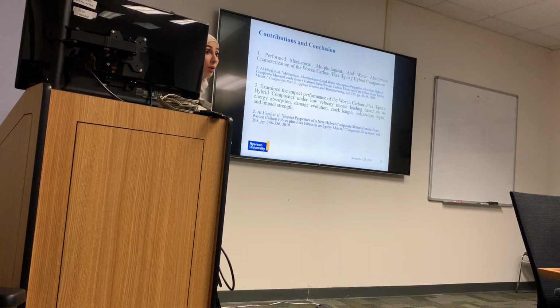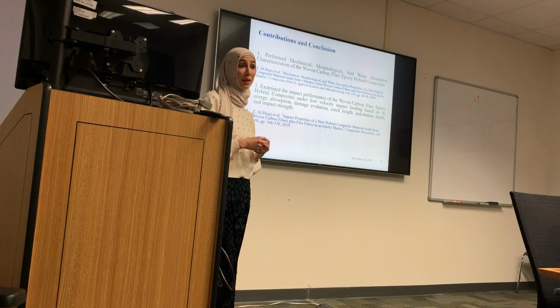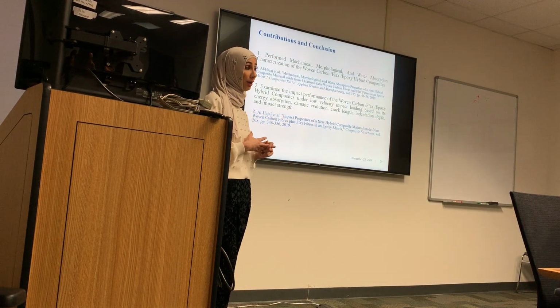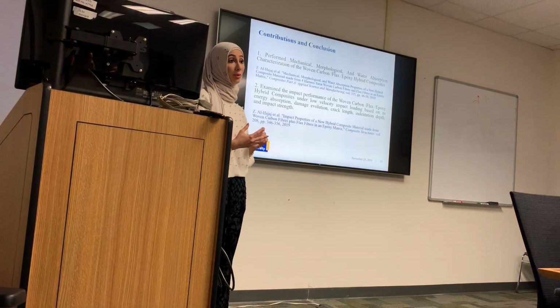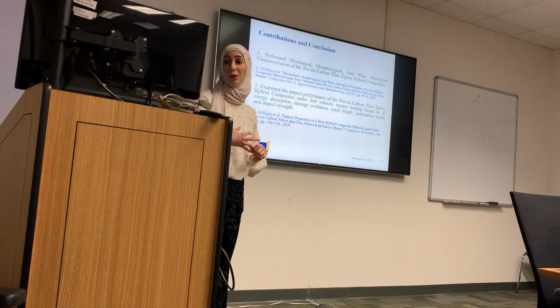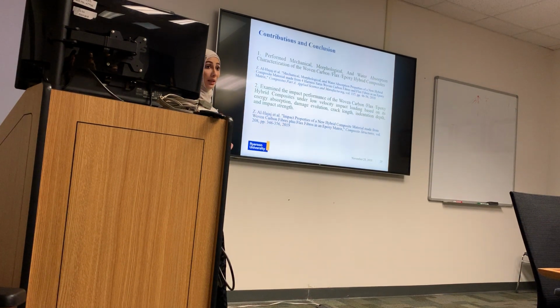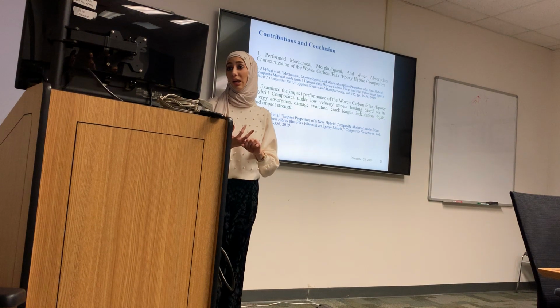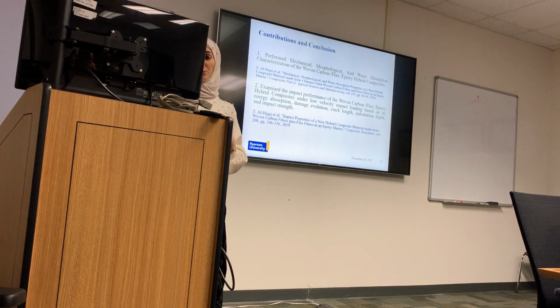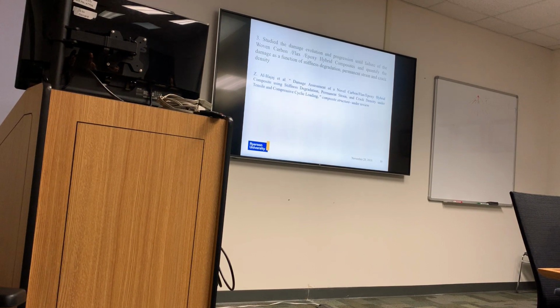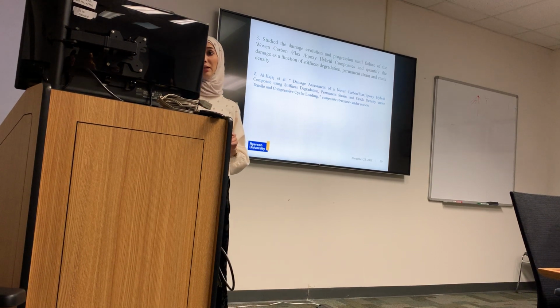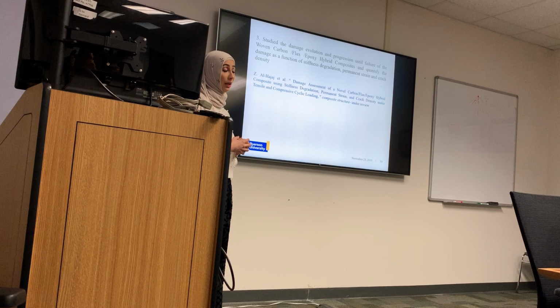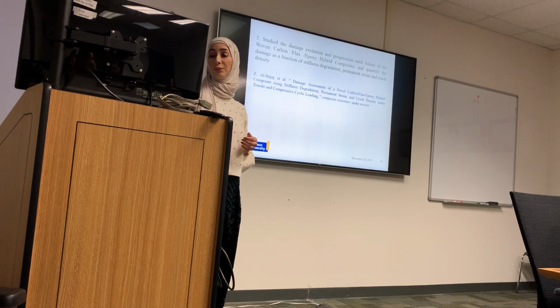In conclusion, I performed a deep mechanical characterization on my hybrid composite, including the water absorption, and that was performed in one published paper. I also examined the impact performance of the hybrid composites at low velocity between 5 to 40 joule, and that was presented in another published paper. I also studied the damage evolution of the material based on their accumulation of damage, accumulation of permanent strain, and crack density. The paper is still under revision.